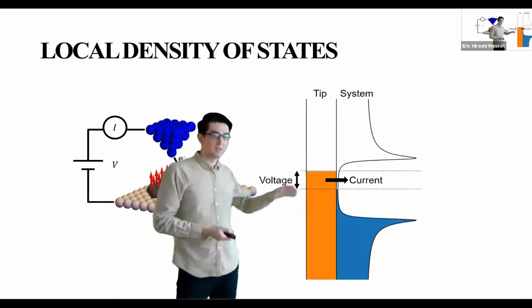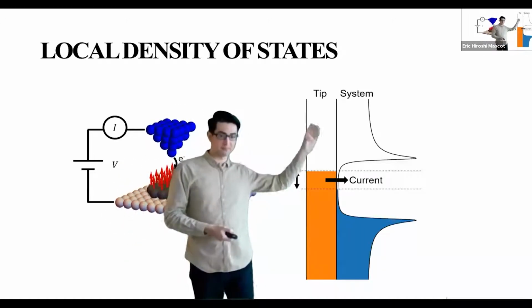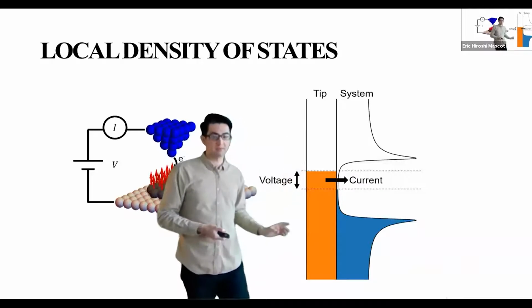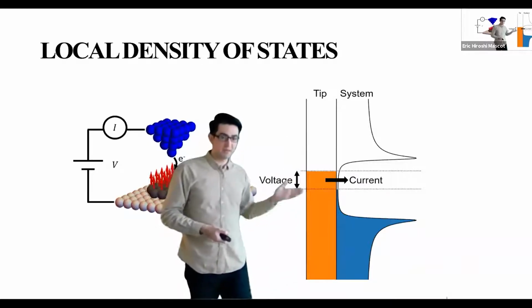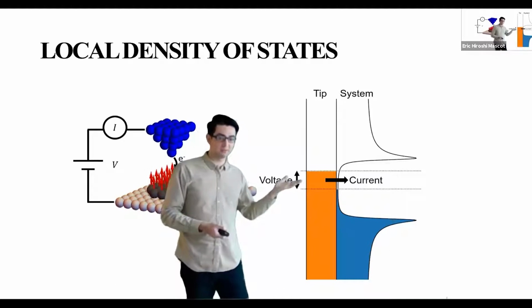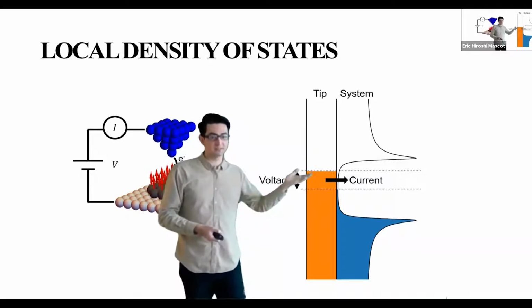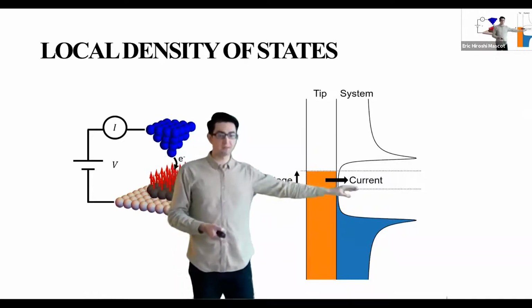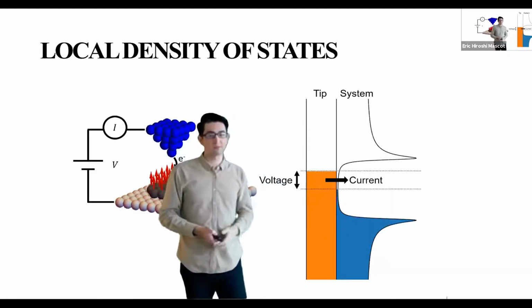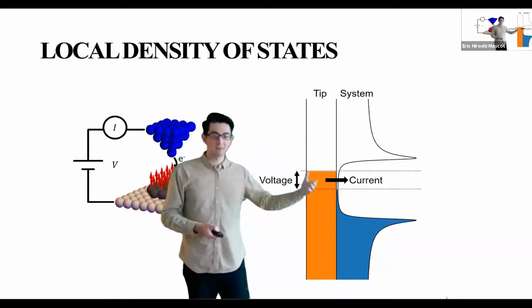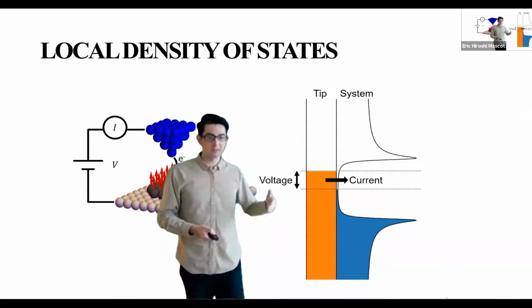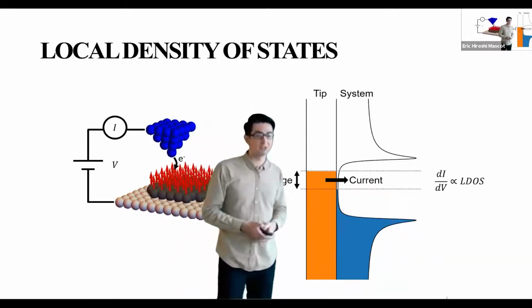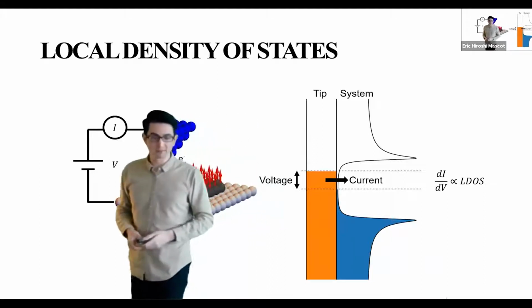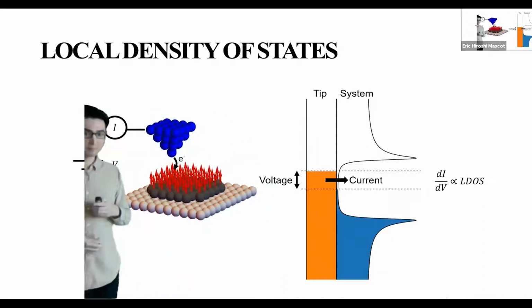And so here's the density of states of the tip and the system. The tip we want to have relatively featureless, and as we increase the voltage, we fill more states in the tip, and those states can tunnel into the system, which we can measure through the current. And so as we look at how the current changes as the voltage changes, we can get the shape of the local density of states.